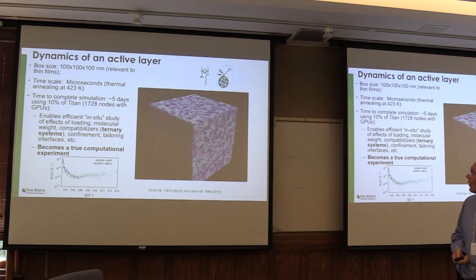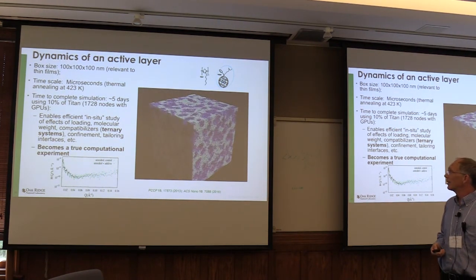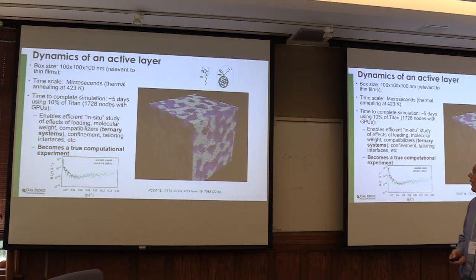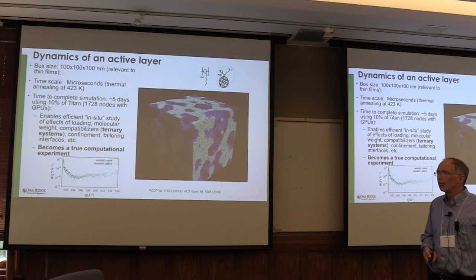If you watch this, you'll see over time the white guys sort of get together and the blue guys get together. And they form these funky domains. And I hollow out the blue guys so you can see the three-dimensional structure, because it gets kind of hard to see in two dimensions. And after a while, you'll see domains form. And if you measure across these domains, they're on the order of 10 nanometers.